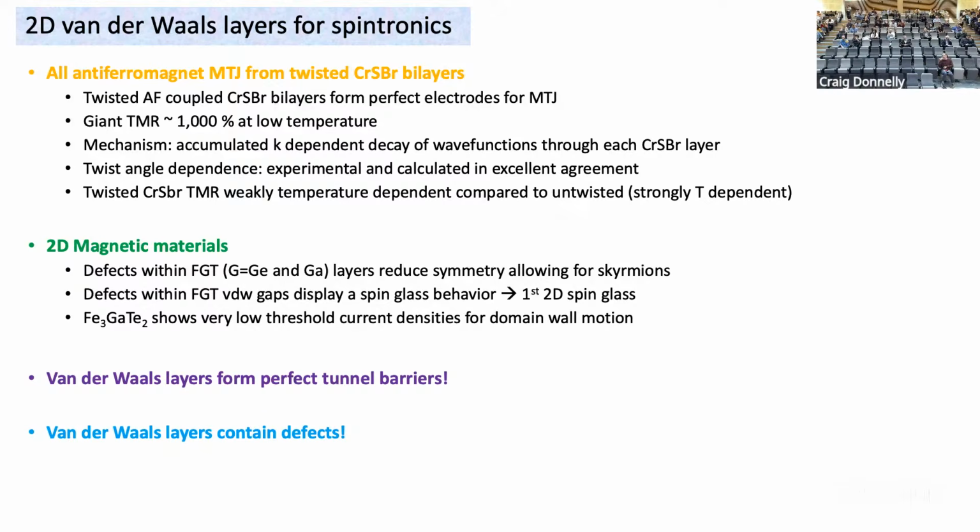The domain wall jumping between defect sites? No, I don't think so. It's certainly an interesting question whether the domain wall could bend locally because of local defects. This is not what we see, at least from optical measurements, where we can directly determine the domain wall. As it moves, the domain wall will actually tilt. We can see all these tilting mechanisms, but because of pinning, the domain wall remains tilted after you've removed the current. So pinning is very important. But the domain wall does not jump from one state to the next. It's a more uniform pinning potential.